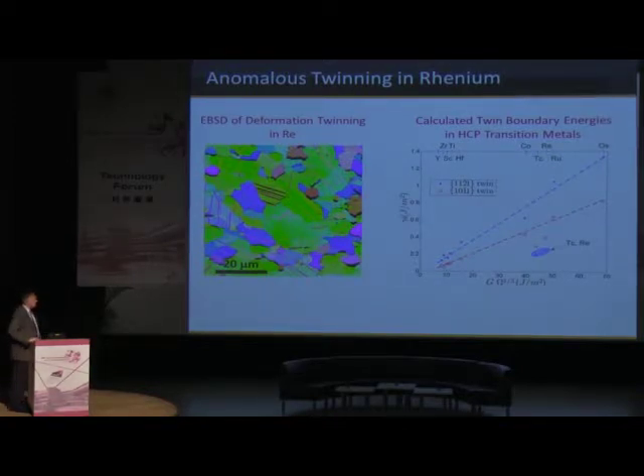So what we ended up doing was a set of high throughput calculations where we calculated the twin boundary energy for all the HCP transition metals, many, many different possible twins. I'm only showing results for a couple here. And I'm plotting those results versus the shear modulus here. And what you see is that for these two different kinds of twin boundaries, for most of the HCP transition metals, there's a nice correlation. But rhenium is sitting way down here. It has an extremely low twin boundary energy.